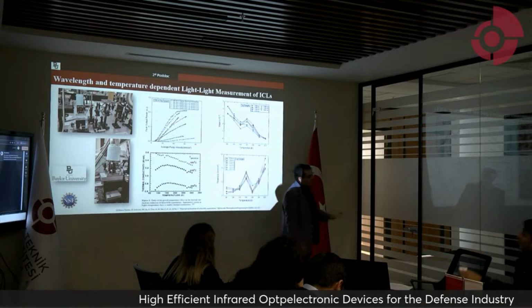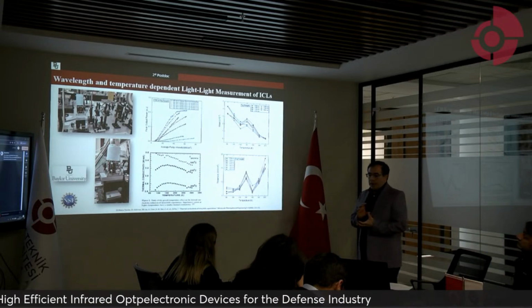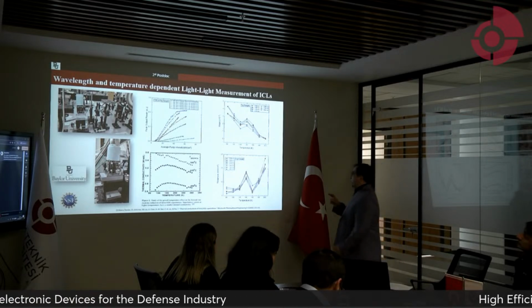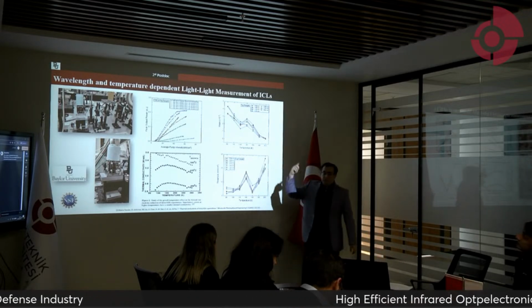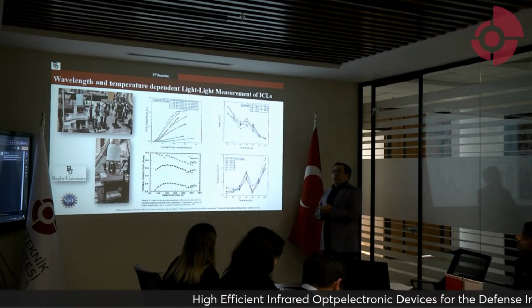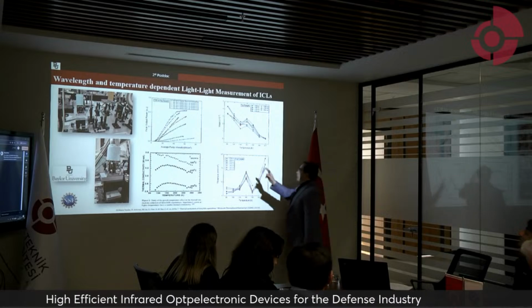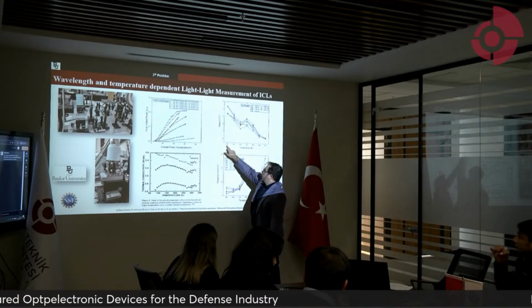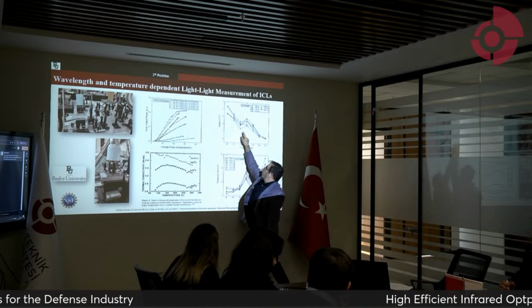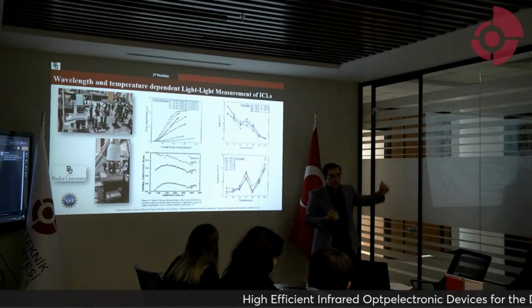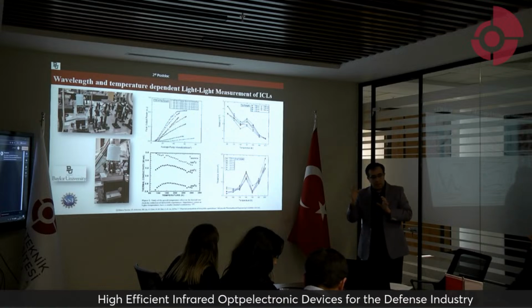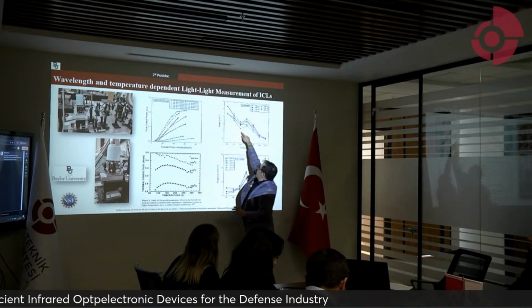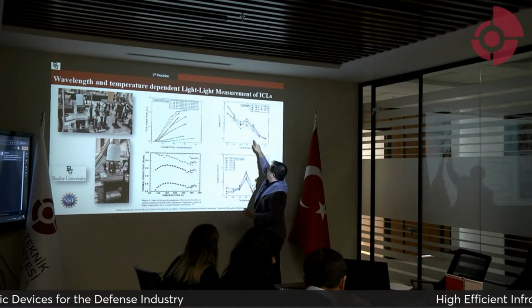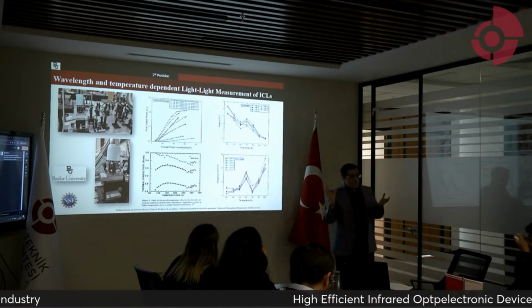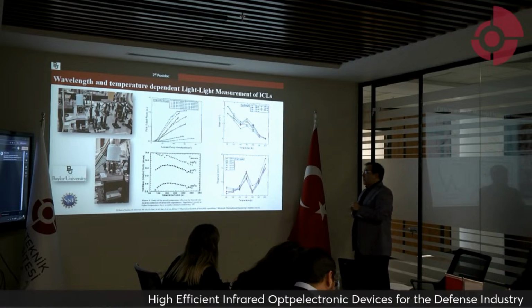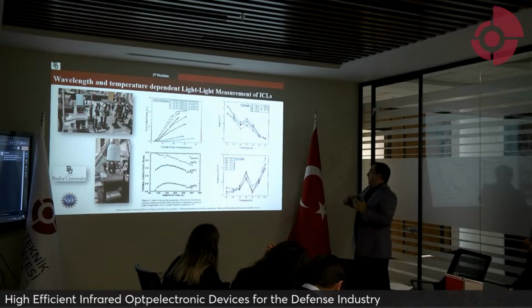Here there was a problem. They saw some problem in this graph, which they did many times, but my professor said there should be a problem because when you increase the temperature from 80 Kelvin to 100, the slope somewhat gets better. Normally, when you increase the temperature, the slope should get worse, meaning decrease. Actually, they couldn't understand what was going on in this system.